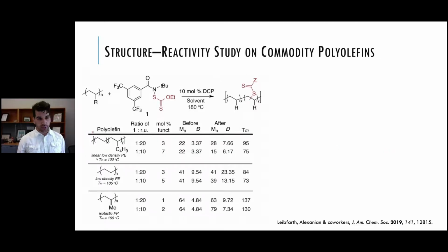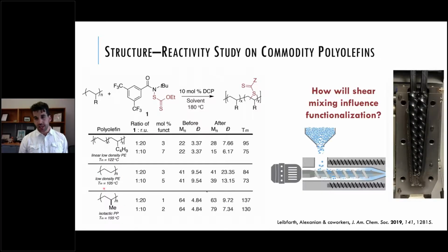So we did it on linear low density polyethylene, which is the predominant material used in plastic packaging, low density polyethylene, and isotactic polypropylene. And we even did this chemistry in an extruder. So in this case, we didn't use any solvent. Again, this reagent is a powder, this polymer is a powder. We mix those two polymers together, we put them in an extruder.